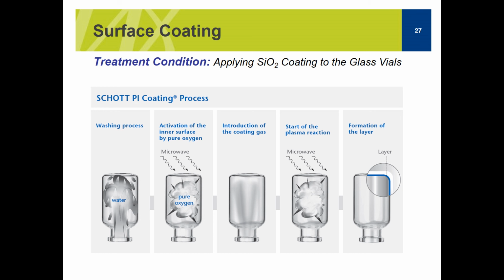But before we talk about the results, let's talk about the manufacturing processes. So Schott, again, produces type 1 plus vials, and these vials do have the SiO2 coating on them. So basically, they manufacture a regular vial. The vial comes in, it gets cleansed by water. After that, it goes through a microwave, and basically you activate the surface by applying oxygen. So this is a plasma treatment right here. After that, you introduce the coating gases, and really what the coating gases are in this case is silicon oxide and some other noble gases that can help facilitate the reaction. You allow the reaction to take place again via plasma, and then bam, you have your SiO2 coating on that side of the plate. Now this SiO2 coating, again, it works, but it has its limitations.